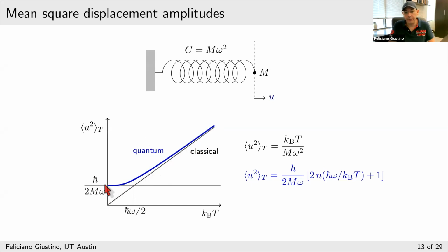So this picture is very simple, obviously, but it is very useful to keep in mind when it is useful to use, for example, molecular dynamics to study temperature effects, and when that is not appropriate. For example, if your system is being considered in this regime, maybe you can use molecular dynamics very simply, but if you are in this regime, obviously that will not cut it. So the important thing to remember is that the divide between, let's say, the quantum regime and the classical regime is half of the characteristic phonon energy.